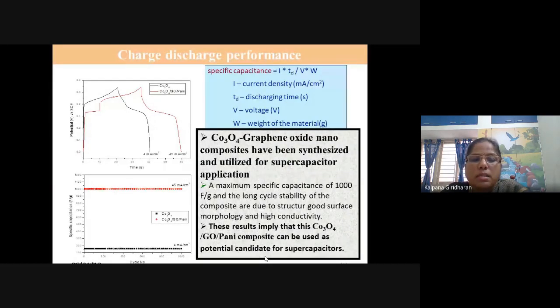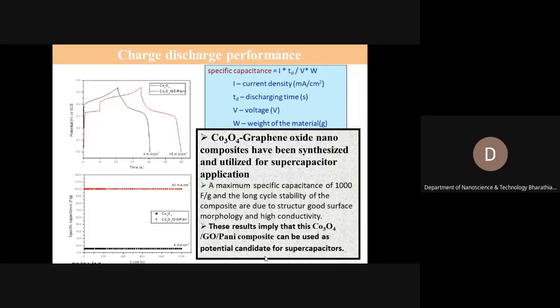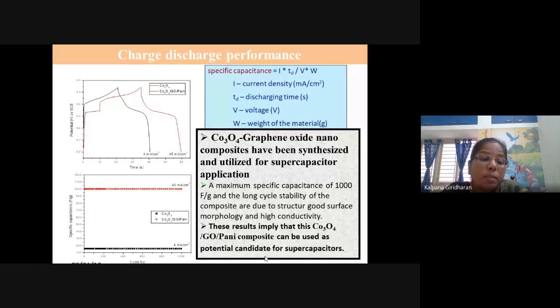And this charge-discharge cycle is typically showing the battery-cum-capacitor behavior, and it gives stable specific capacitance of around 1250 farads per gram at 4 milliamp per centimeter square.